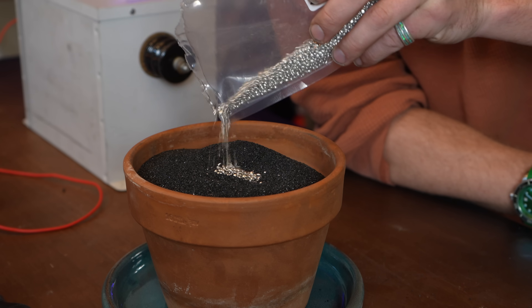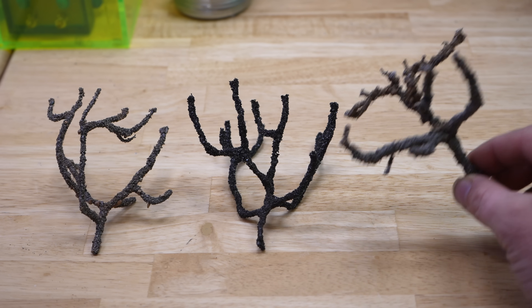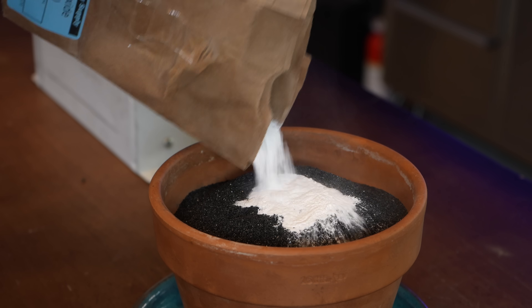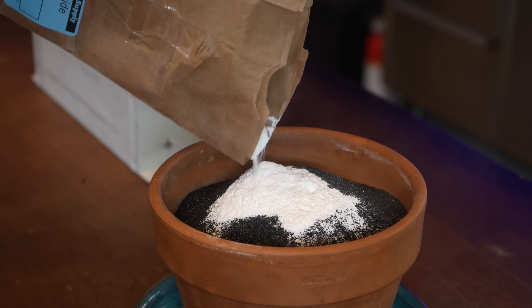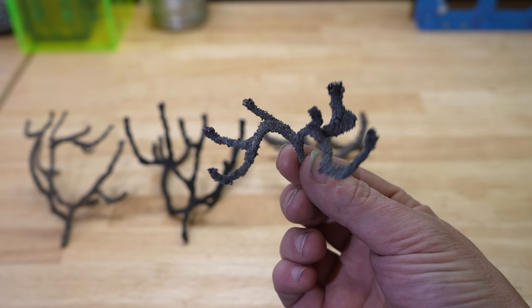Next, I tried a couple additions to the sand, hoping it would help with strength or structure, and I really thought I was a genius. First, I tried adding tin with the idea that it would melt easily and bond with the sand grains. This definitely led to a strange result with thicker channels that were even more fragile — it looked hideous. Then I tried adding alumina powder, which is a common glass additive for increased strength. This led to a very clean melt with the strongest glass yet. There was actually more to this fulgurite until I dropped it. With each attempt, I learned more and more about the challenge that is glass production.